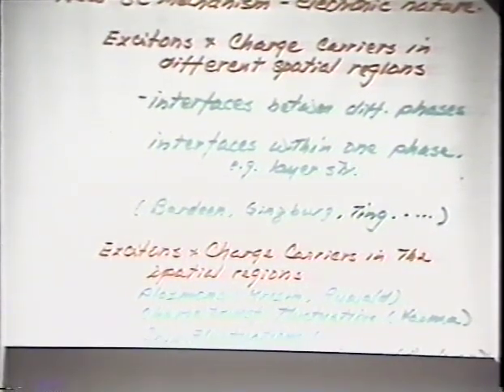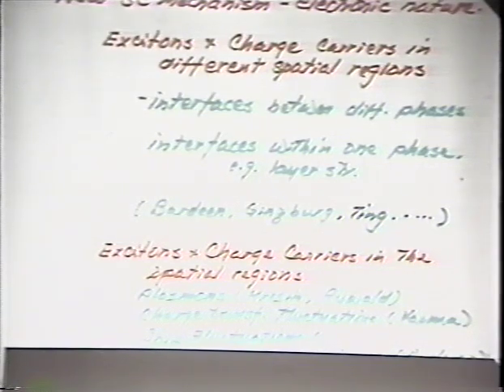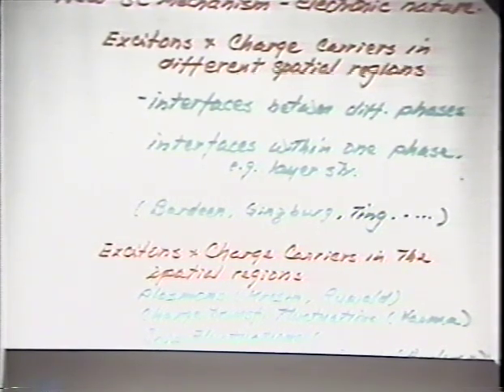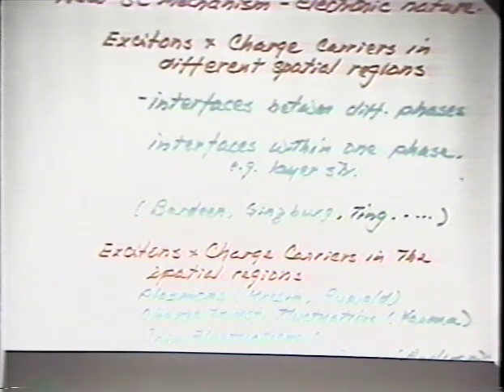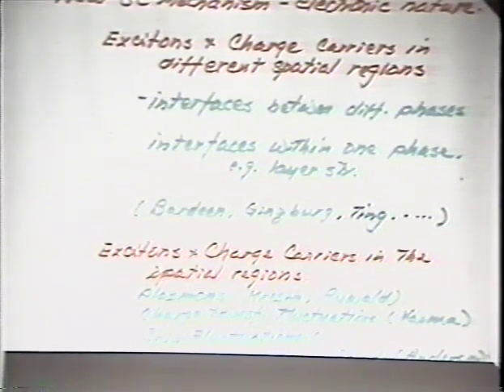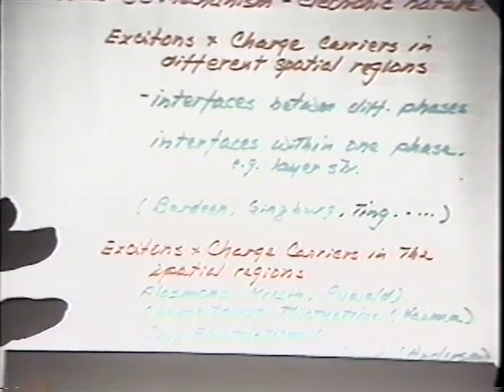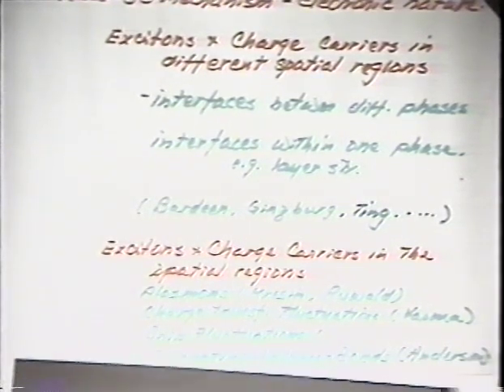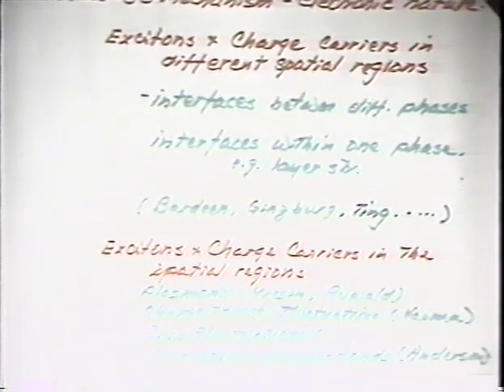And then the other type is perhaps when you look at all this material, they all have some magnetic origin in it. As we observed previously, the material lanthanum barium copper oxide, you can make it into insulator, you can make it into superconducting, you can also make it into magnetic situation or magnetic compound. So here we are talking about a possibility of spin fluctuation associated with the copper 2+ ions, and that can enhance superconductivity and get a D-pairing, just like people proposed in the heavy fermion situation. And then the other model is resonating valence bond state proposed by Phil Anderson, and it appears to us at this moment there are no experiments which can distinguish one from the other or rule out any of these, and I think they all deserve some